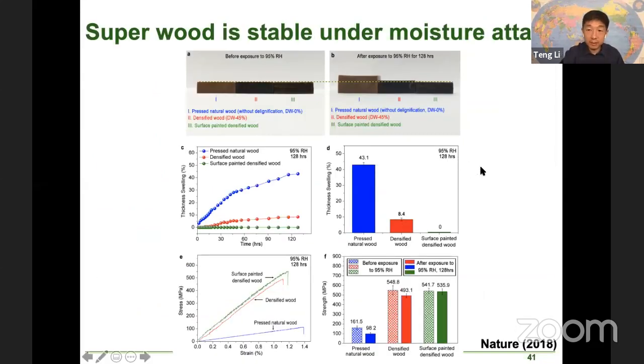Superwood is stable under moisture attack. We did the accelerated test in 95% relative humidity for 128 hours. It showed that it does absorb water and swell by 8.4%, and there is a modest decrease of the strength after absorbing water, from 548 megapascal to 493 megapascal here. However, this can be easily overcome by doing a very simple surface coating.